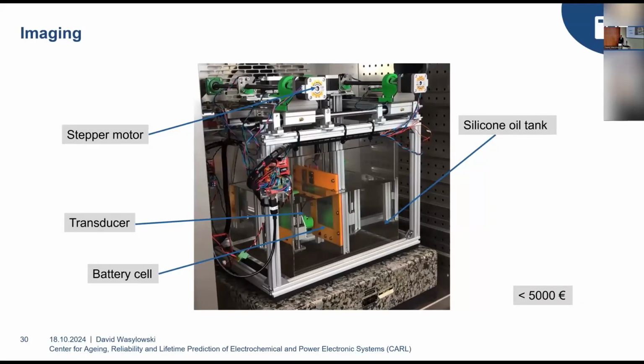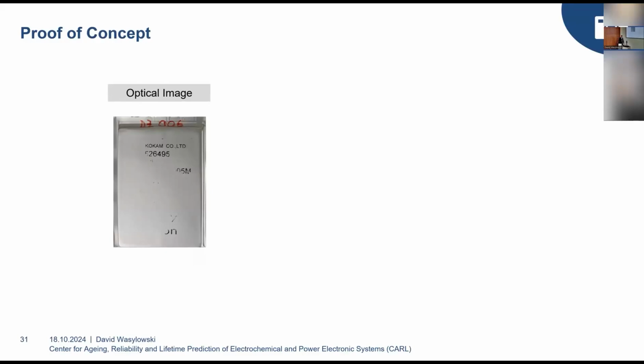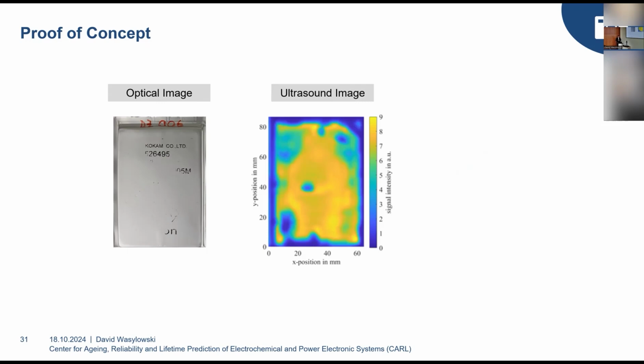So in order to verify whether this device is actually working, our former colleague Jörg Fuchs gave me the cell, and he came to me and told me that this cell is somehow aging much faster than he expected. And he asked me to take this ultrasound image to visualize what's inside of the cell and if we can see anything that might explain this fast aging speed. So this is the first ultrasound image that we generated from this pouch cell, and we can see, first of all, this outline of the battery cell is pretty well visible in this ultrasound image, but besides this yellow plane, we see a bunch of blue and green islands scattered across this battery cell.